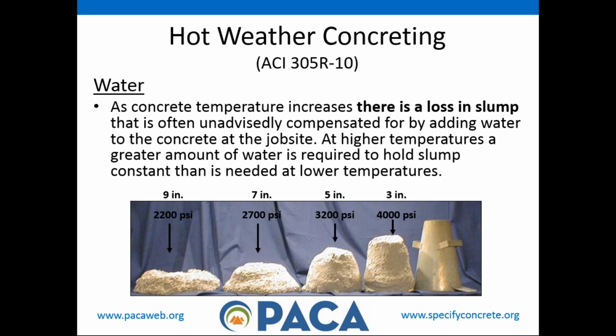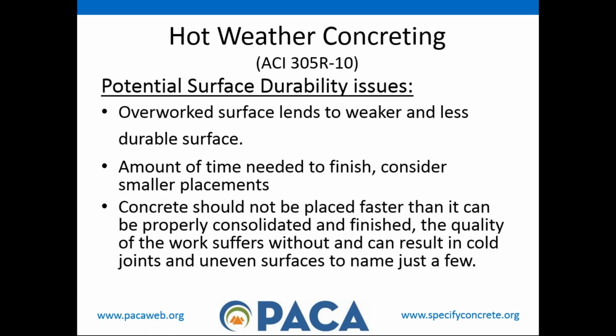Well, we mentioned water. I mentioned about putting too much water in. Look at the strength loss just based on adding water from a 3-inch slump that was designed at 4,000. Now you're up to a 7 with water. Look how much you lose there, 1,300 psi. You can never get that back. Not to mention the curling you can incur and the cracks that you'll incur.